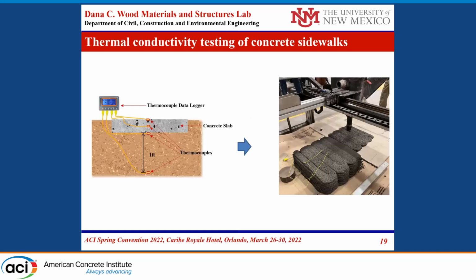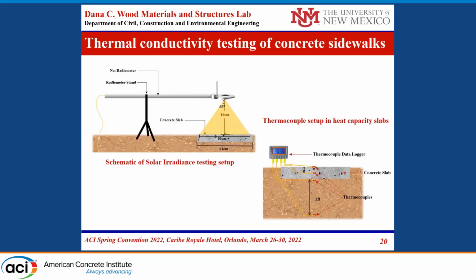Some of the testing we are doing, we are measuring the thermal conductivity. We are placing these 3D printed slabs on sand or soil specimens that are 1 foot deep, and we are adding thermocouples, and we are measuring the heat that it absorbs during the day and the heat it emits in the evening, comparing it to our mix that is not 3D printed, and to the standard sidewalk concrete mix, which is again 4,000 or 5,000 PSI, having a lot of cement. And again, we use this schematic for the solar irradiation testing setup to measure the irradiation. Again, a lot of this is ongoing as we speak.